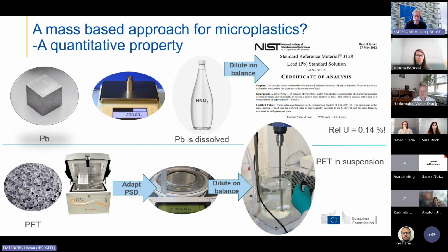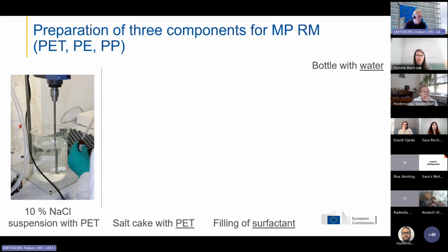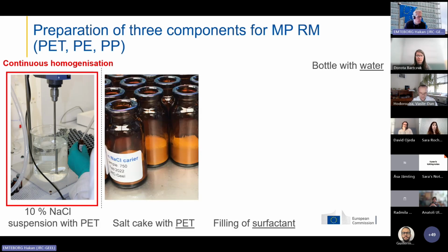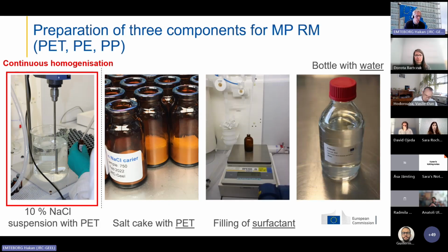And this was what we started quite a number of years ago. The question is how reproducibly and how well could you actually do this? There's no risk that you will be as good as for the lead example, but is it usable? So I show again this suspension here, 10% sodium chloride. We prepare out of that a salt cake, because that suspension with the PET particles embedded into it is freeze-dried, so the microplastic particles are immobilized in the salt cake. And we prepare a surfactant that we provide to the customers and a bottle with water. And then the whole idea is that the microplastic particles are rinsed out of those vials into the bottle of water using the surfactant, and you have your ready-to-use reference material for a certain number of microplastic particles per liter, or a quantity, in that case, microgram per liter of microplastic particles.